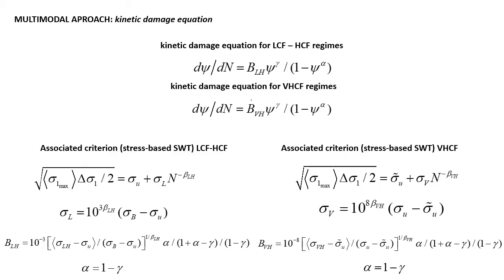The two-parameter kinetic model of fatigue damage accumulation was used. The parameters alpha and gamma determine the damage accumulation rate. In order to simplify the analytical solution for the damage function, the following link between these parameters is chosen: alpha equals 1 minus gamma. In order to describe the evolution of fatigue damage in metal, the following kinetic damage equation was used for the low, high, and very high cycle regions.